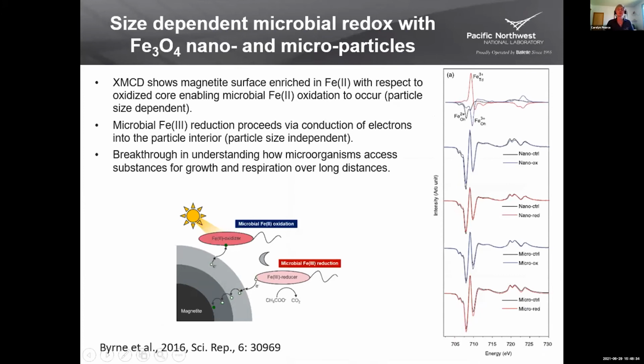So that was looking at oxidation and reduction by separate cytochromes, but this was a study by James Byrne that shows that magnetite can cycle between the oxidized and reduced form, and so it can act as a recyclable electron donor and acceptor for iron metabolizing bacteria in the environment. And so James wanted to study how, when you turn the light on and you stimulate the iron oxidizers during the day, what pool of iron are they accessing in these particles? And then when you turn the light off at night and you activate the iron reducers, how are they extracting or donating the electrons back into the structure?